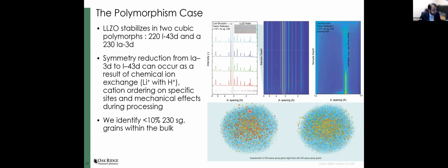The reason why we think this happens is because we dope these LLZOs with a dopant material, and we cannot really control the local concentration of these dopants as we sinter these materials. And the differences in dopant concentration locally can lead to some of these differences and the formation of these two space groups that we are seeing.